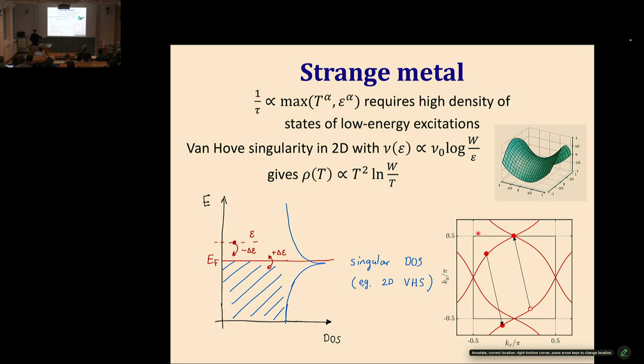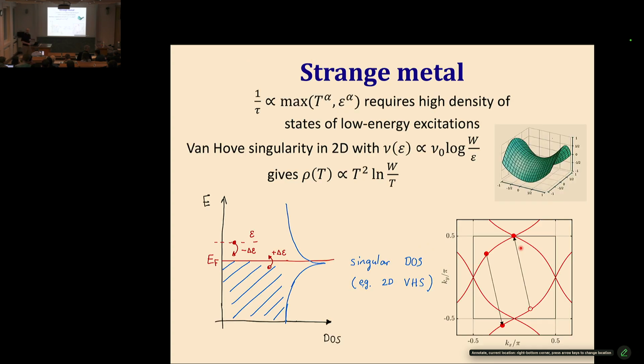So luckily, as Michael showed, we do actually have an example where we can do exactly this. And this is really the example that got me actually thinking about this problem. This is strontium ruthenate, where by applying strain, you can really control the Fermi surface of the system and tune it to basically sweep the Fermi surface across this topological transition of the Fermi surface.